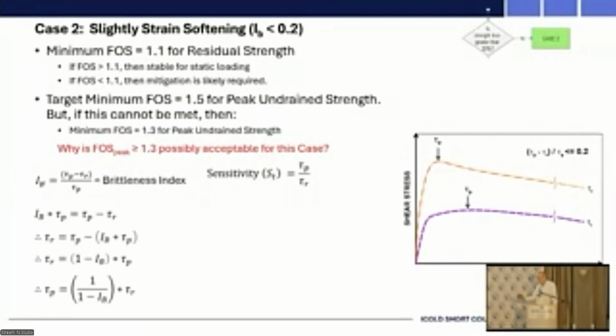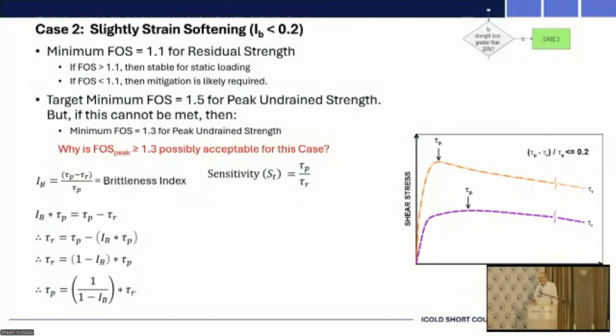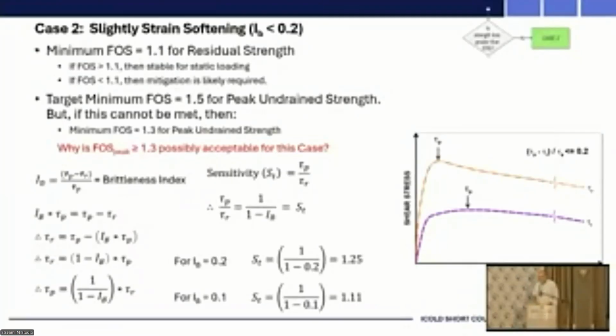And if you apply basic mathematical principles, I'm not going to walk through them step by step, but you can read that in the paper or in the presentation. You get to an outcome of peak strength is equal to 1 over 1 minus the brittleness index times the residual strength. And so then if you divide by residual strength, you get the ratio of peak strength to residual is equal to that ratio of 1 over 1 minus I_b. And that can be defined as the sensitivity ratio. I just use sensitivity because it's easier to plug into these later equations. And so if you have a brittleness index of 0.2, you can do the math. You get a sensitivity ratio of 1.25. If you have a brittleness index of 0.1, you're going to wind up with a ratio of 1.11.